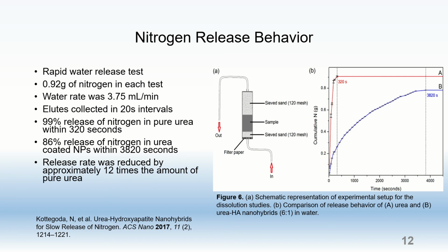The data obtained is shown here in figure 6b, where 99% of the nitrogen in pure urea was released in the first 320 seconds, as opposed to 86% release of the nitrogen in the urea-coated hydroxyapatite nanoparticles within 3,820 seconds. This showed that the release rate was reduced to approximately 12 times slower than that of pure urea.